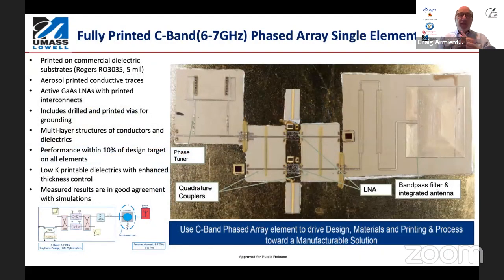Here's an example of some of these things we've pieced together. This was actually done with Raytheon, who was the prime on this America Makes project. This was a C-band phased array element where we integrated a variety of different printed devices in the microwave region. This happened to be on a Rogers substrate. What you see here are things like a phase tuner, quadrature couplers, and I'll talk a little bit more about that. We've got some gallium arsenide chips in here where we've interconnected them with a printer, not wire bonds. We have a bandpass filter and antenna all integrated together. So we worked on these elements separately, and then we put them all together on this America Makes project.